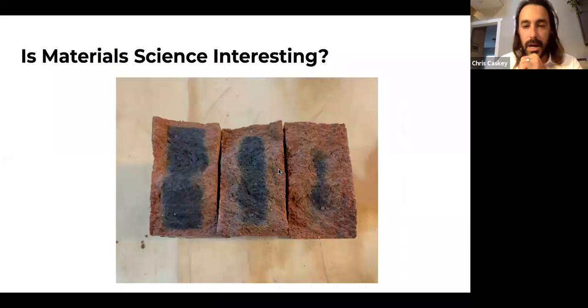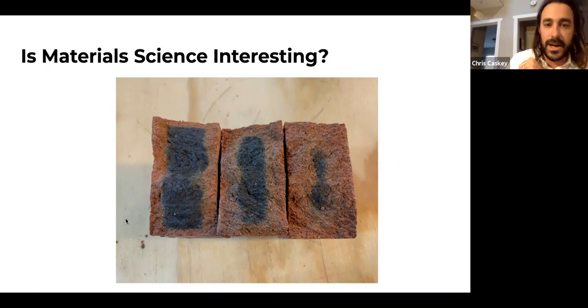This is an experiment that we did to see how we were burning out. We did a series where there were different temperatures that we held at and different lengths of time to watch. What's happened here is the oxygen has worked its way in, reacted, gone back out, and we stopped the firing at different times to see here's where it is still visible carbon, and then that shrinks and shrinks.